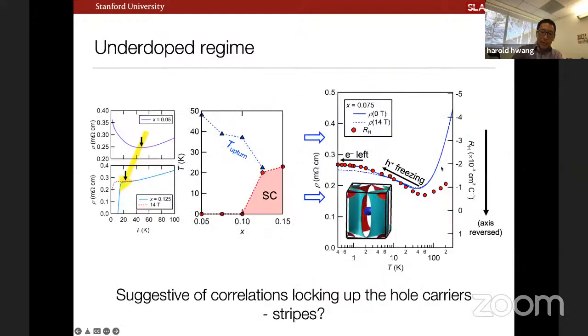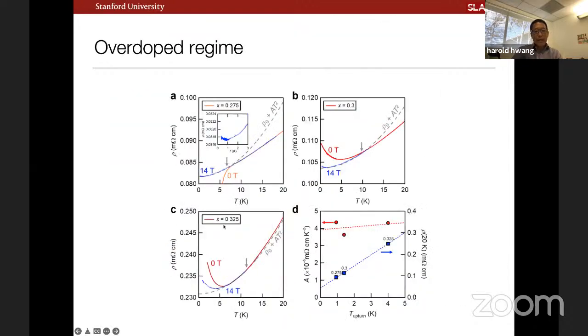But let me also take an opportunity to flash one other data set. So this is kind of how transport looks now in our cleanest overdoped regime samples. So this is just at the edge of the dome. So this is in orange superconducting. We can suppress that by magnetic field, right? And it's pretty well described by a T-squared fit, right? Okay. But there's still this very tiny feature, but to be fair, there's a slight upturn at the lowest temperatures. And you can see that this upturn feature is still living there and can be suppressed by magnetic field. It qualitatively looks like localization, magnetoresistance in this regime.